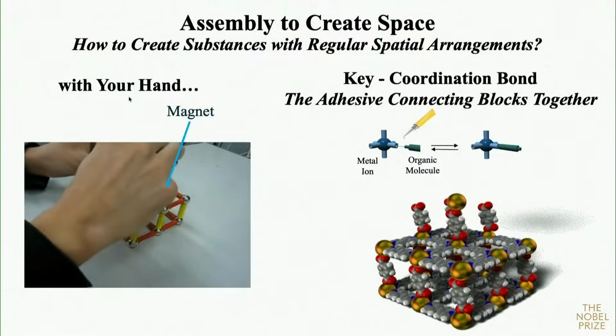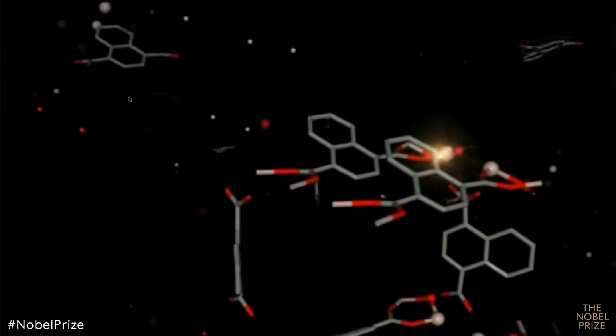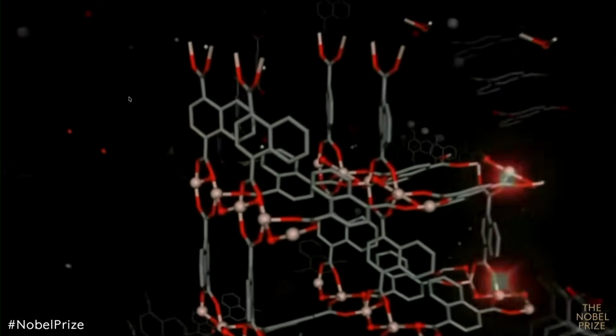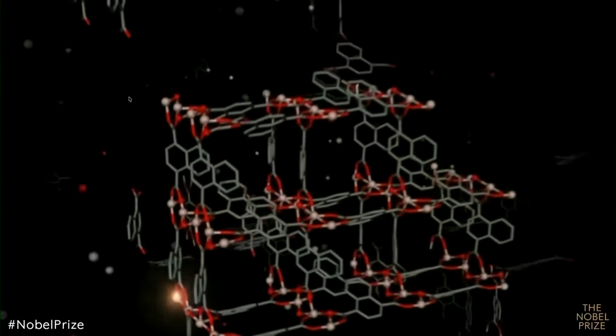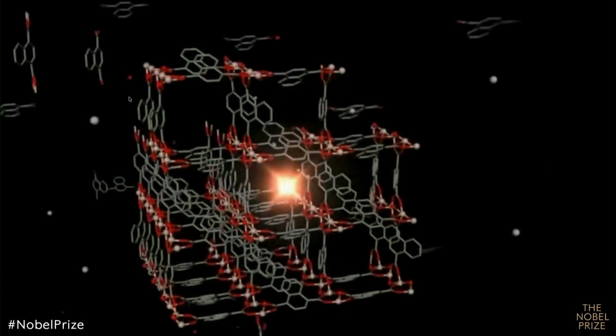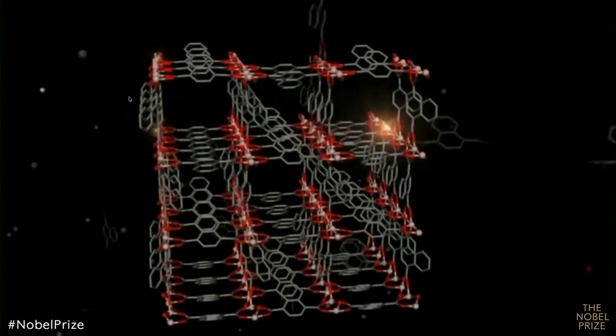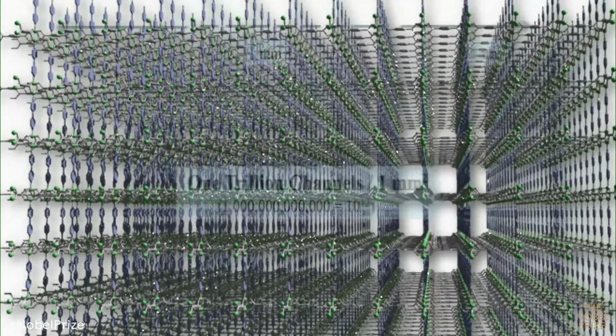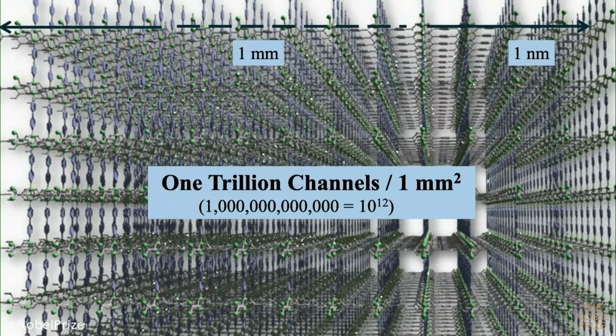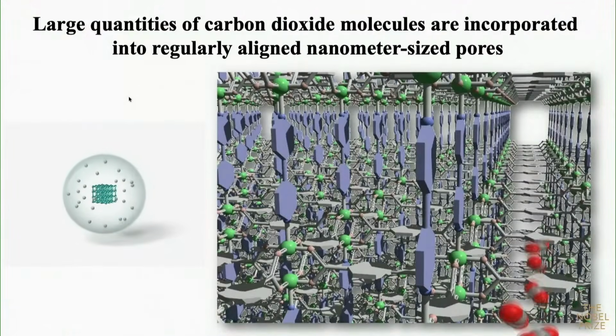Coordination bond connects metal ions and organic molecules like this. So you have the organic molecule solution and the metal ion solution, and you mix. In a few seconds, you can get this kind of framework. And also the crystal, very beautiful. For instance, this is a 1 millimeter crystal. In the crystal structure like this, the unit is 1 nanometer. So one side has 1 million channels, and the vertical side also 1 million. Totally 1 trillion channels per 1 millimeter crystal. That's enough to absorb and capture gas materials like this.